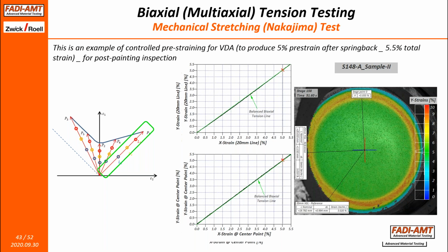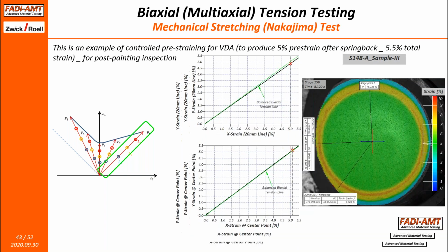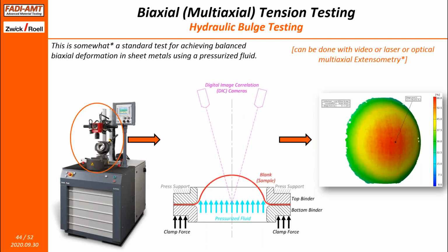As you can see, the X and Y ratios of strains are exactly the same. And then we can take the sample to about 5.5% before we retract it back with a spring back of 5% to achieve a specific amount of strain, which happens to be 5% in this case.